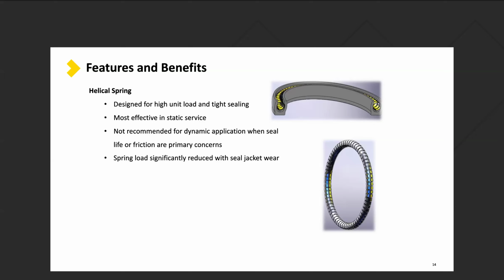But as long as you stay within the parameters of our load versus deflection curves, this is a very, very reliable spring. For really high load, we can even double wrap it, where we would take the standard spring and then wrap another coil internally to significantly increase that load. That comes into play for light gases, cryogenics, things like that, where you don't have a lot of pressure, but you need a tight seal. This is a great seal, or spring.